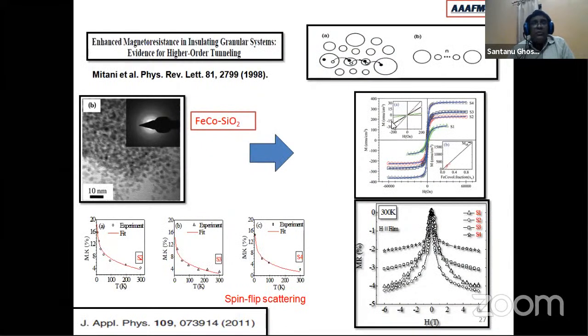So we thought that we can use our granular system for tunneling magnetoresistance measurement, because all our individual metal nanoparticles which are separated by an insulating matrix could be one mini tunnel junction, and there are millions of such tunnel junctions in a sample. And in 1998, there was a theoretical paper published by Mitani, who indicated such materials could be very good for TMR. And we have done a series of measurements on various samples. However, we could see around 20% TMR at low temperature, which eventually decreases, and it happens because of spin flip scattering.